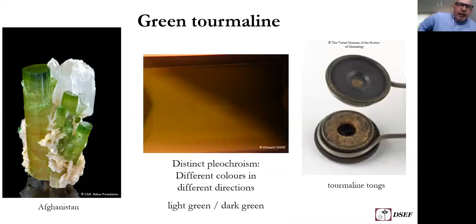Now, if you look at the tourmaline, here you can see a very nice crystal from Afghanistan. And if you look at the tourmaline using a two-field polarizer to observe the pleochroism, you will see that the pleochroism in tourmaline is very distinct. As you can see here, this is the line that divides the two polarizing fields, and you can see a lighter color and a darker color.